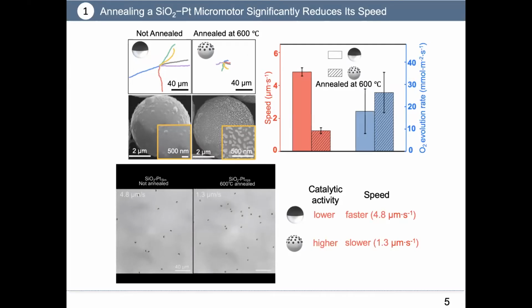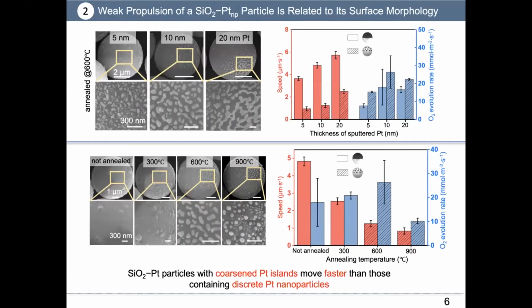Surprisingly, by measuring the oxygen generated from the decomposition of hydrogen peroxide, we found that the platinum nanoparticles showed better catalytic performance. On the other hand, by systematically changing the thickness of platinum and the annealing temperatures, a sharp decrease in motor speeds was also observed. We confirmed again that annealed samples often showed better catalytic performance. So the significant difference in the motor speed cannot be attributed to the difference in their catalytic performance, but to their surface morphology.